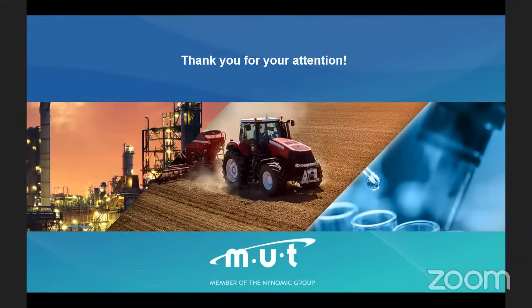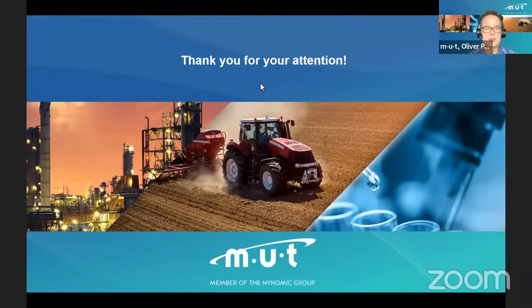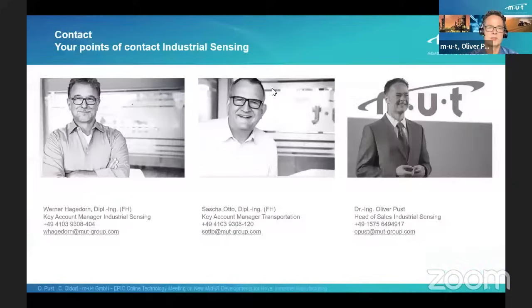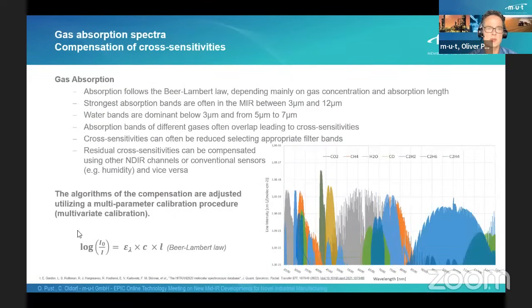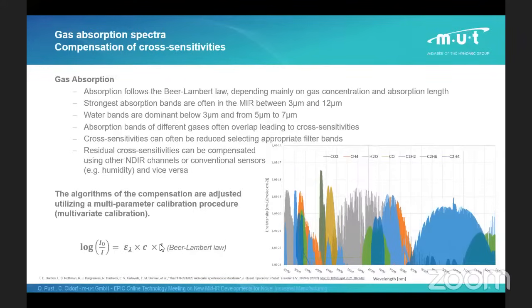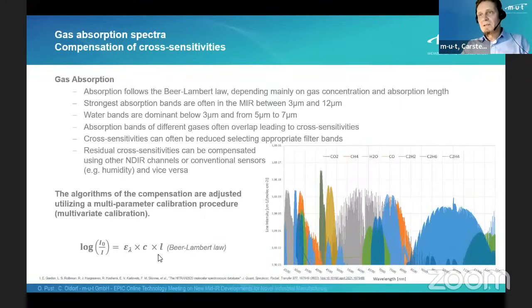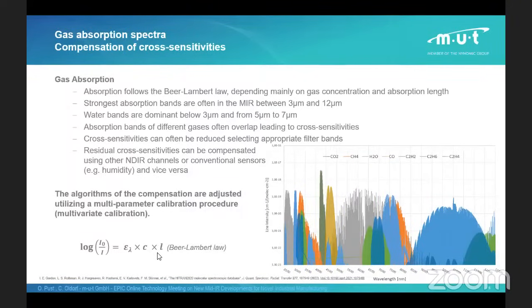Can this system be made more compact, like by reducing perhaps the number of gas targets? In principle, it can be made more compact by different means, but not necessarily by fewer gases. So the principle stays the same, but it also depends on the concentration you want to measure, how compact it can become. Carsten has brought up the formula that defines more or less the dimension of the gas cell. Well, the absorption of the gases depends mainly on a gas-specific absorption coefficient, the concentration and the length of the absorption. This is what is in the Beer-Lambert law. So you need the length to get to low concentrations.